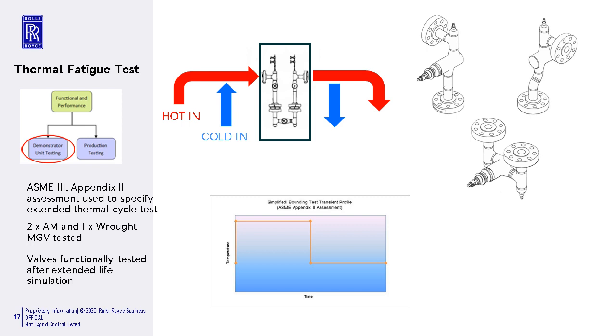So the ASME acceptance for this test is that no through-wall defect is generated throughout the test. However, we also paused the test a number of times just to check the valve's functionality in terms of seat performance. Again, all valves successfully passed this test.